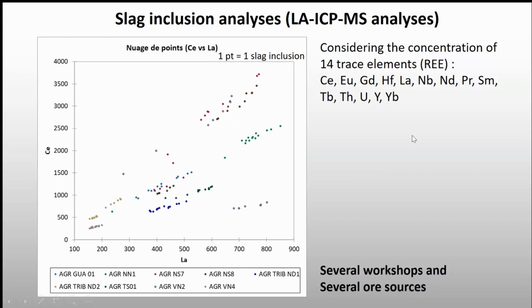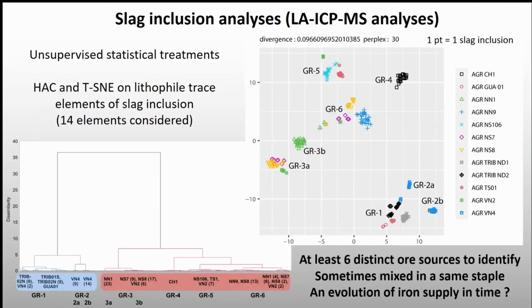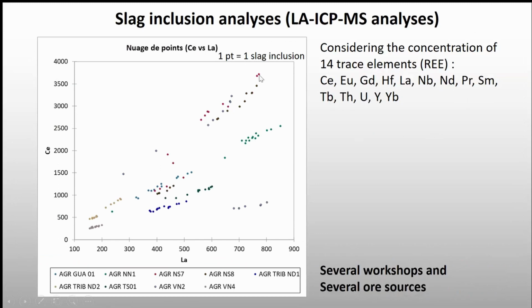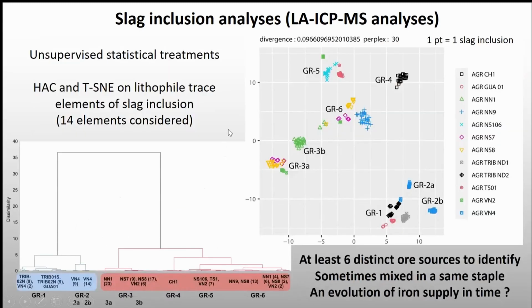So as there's many elements, and to try to have a global look at these elements, we usually use statistical treatments. We prefer the unsupervised statistical treatments, to make sure that if during the treatment you regroup two different slag inclusions, it's because they have the same composition and not because they come from the same sample. Maybe I forgot to say here that one dot is the analysis of one slag inclusion. So it's the same on this graph too.